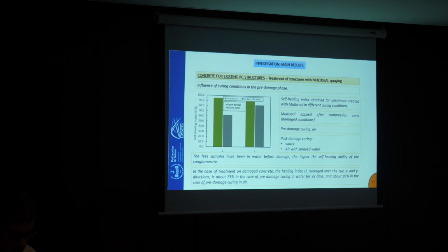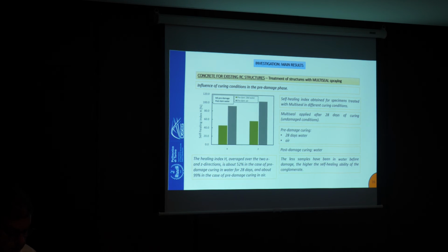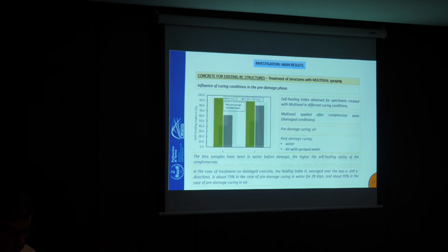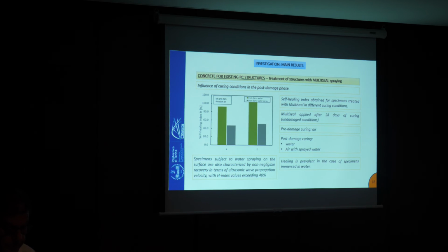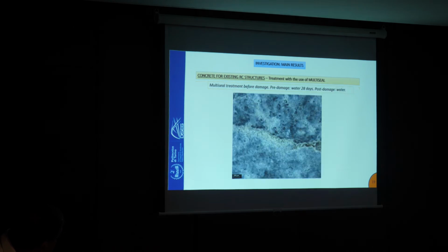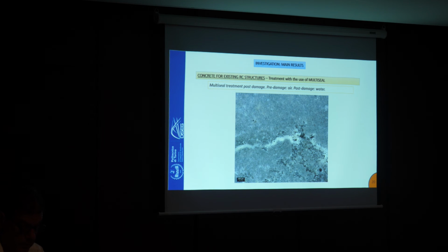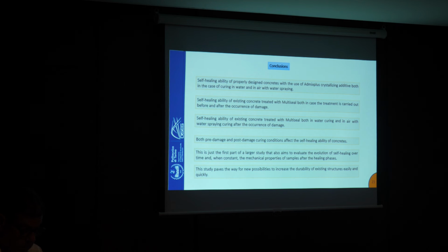And this is confirmed also in case multi-seal is applied in damaged condition. In fact, the previous graph refers to multi-seal applied in undamaged condition, so before the compression test I showed you before, while in this case the multi-seal is applied after the compression stress test, so in cracked concrete specimens. Finally, I show you the evidence of crack closure also for existing structure, and here you can see the conclusion.